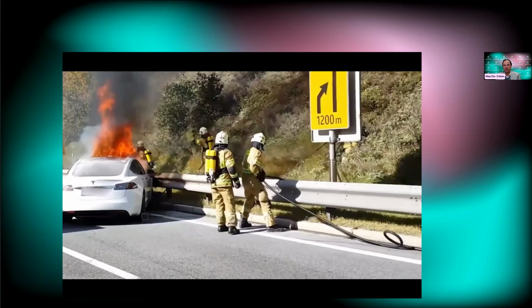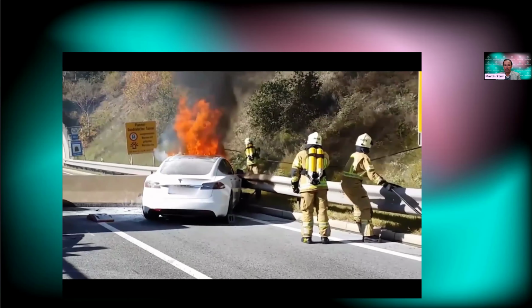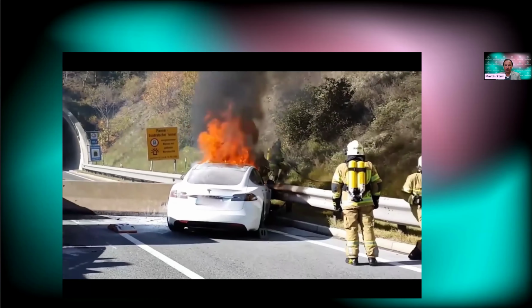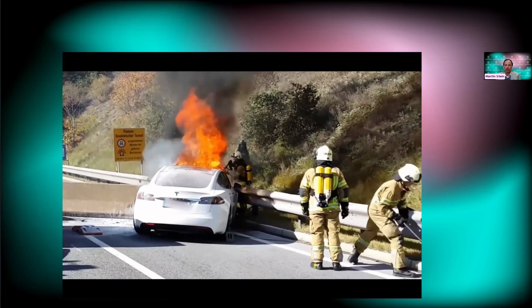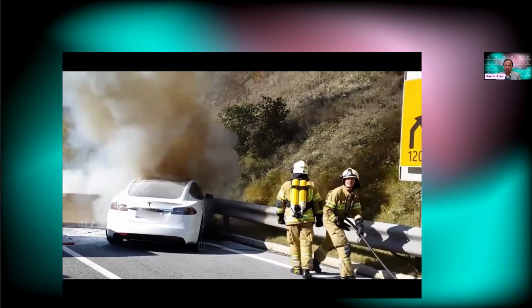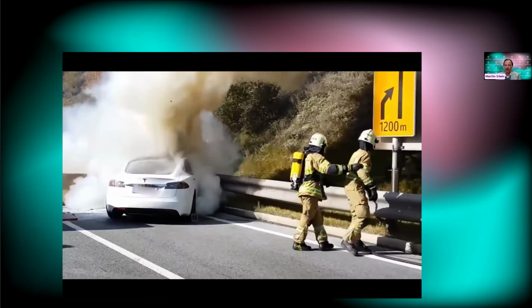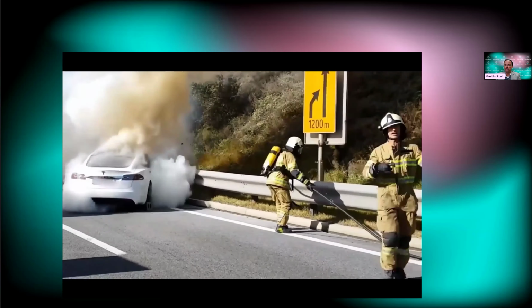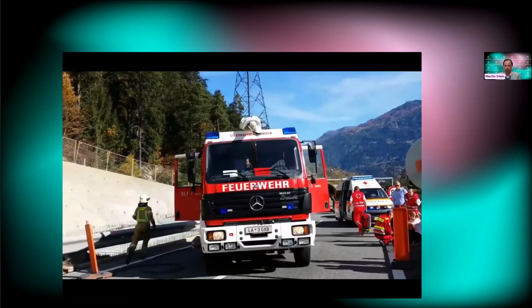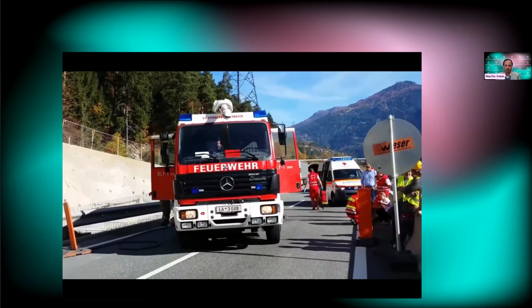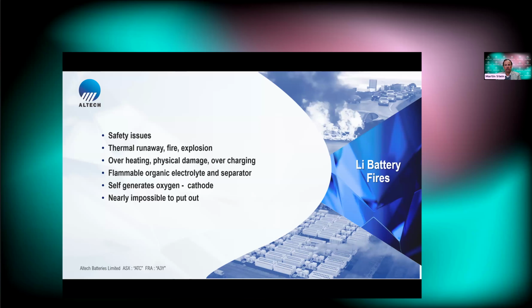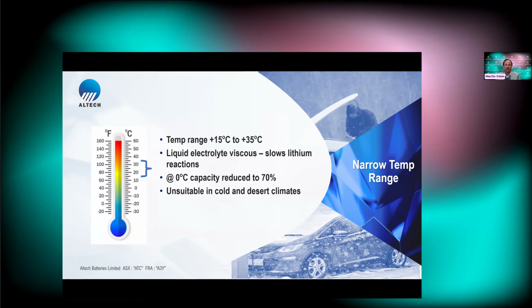Now, I'm sure your viewers have seen the issues with the Teslas and the lithium-ion battery fires. What actually happens is that they get thermal runaway, that organic material catches on fire, and they actually produce oxygen at the cathode level. So that's why you can't put these fires out, because the oxygen's actually produced internally and it's fueling the fire from within. So they have the safety issues, they have the thermal runaway issues, they're highly flammable. Lithium-ion batteries have also got a narrow temperature range.